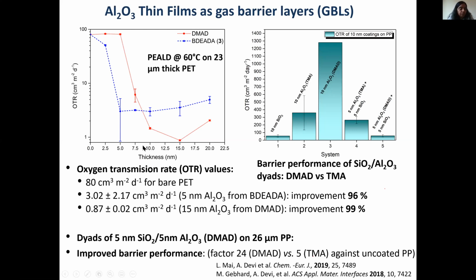So this is a range where we would like to operate, where you have a very good OTR value. If I compare the OTR, take for example the bare PET plastic foil, you have 80 cubic centimeter per square meter per day. Now if I coat, for example, 5 nanometers of aluminum oxide from this precursor, then I bring down the value from 80 to 3. Now if I increase the thickness to 15 nanometers, I bring it down further. So now you see, basically you have an improvement factor of more than 90%.